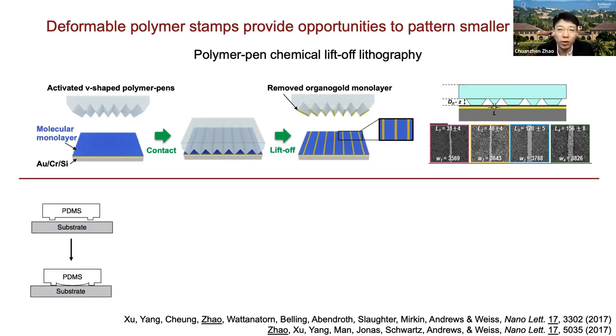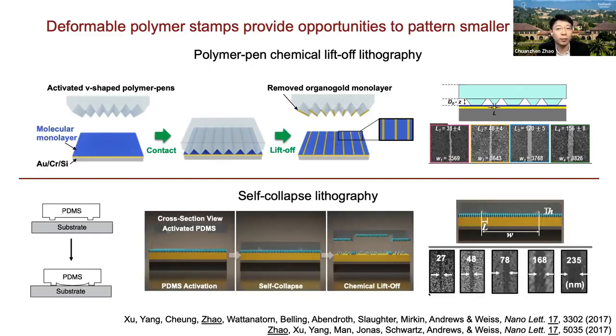Another quite interesting technique we developed is based on a well-known phenomenon called roof collapse. Basically, when a small aspect ratio of height and length is applied, the stamp will collapse in the central area, which is referred to as roof collapse. Generally, roof collapse is considered an undesired phenomenon that people try to avoid in soft lithography, as it cannot replicate the patterns with desired features. However, I always believe that there's no undesired phenomenon in science, as each phenomenon can be used as a useful aspect for different applications. One day I was in the lab and thinking, can we learn something from this phenomenon, or is the roof collapse really bad?